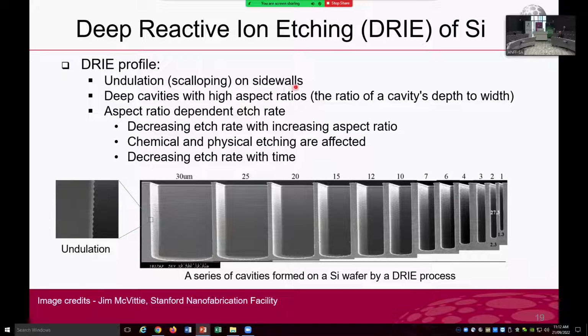Firstly, I would like to highlight deep reactive ion etching's capability in achieving high aspect ratio structures. We can see these very narrow and deep cavity structures, which is not possible with an isotropic wet etching process. An aspect ratio of 50:1 is known to be possible by using a deep reactive ion etching process.